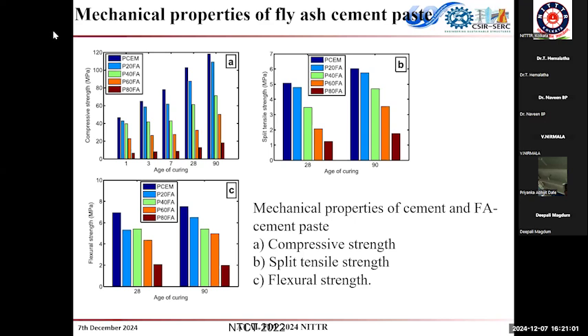Here this is just to show how the strength is affected when we go from 0 replacement to 80% replacement. For different days, when we are using fly ash, we have to see how the early age strength is affected, and we have to go beyond 28 days because it is pozzolanic in nature. So unlike ordinary Portland cement, when we incorporate fly ash, we can expect strength improvement even beyond 28 days.